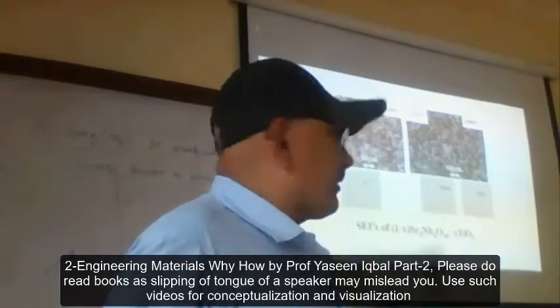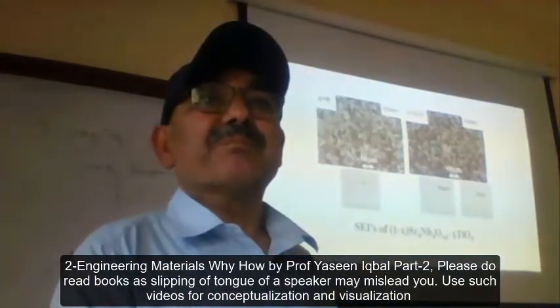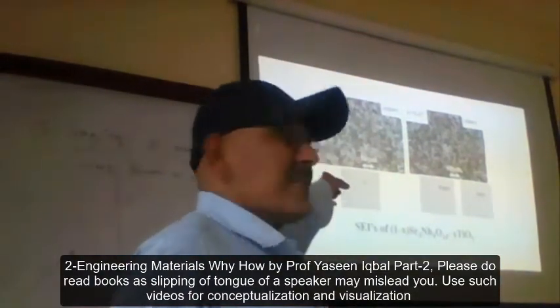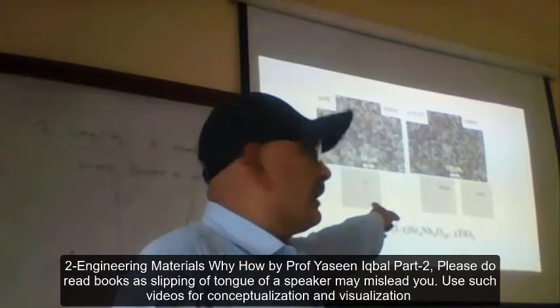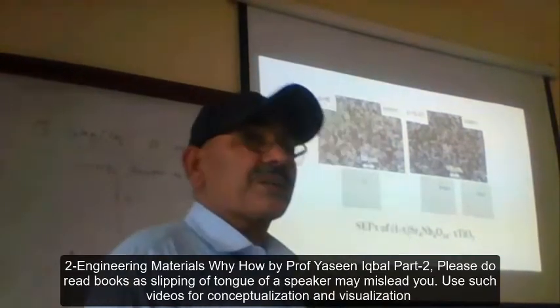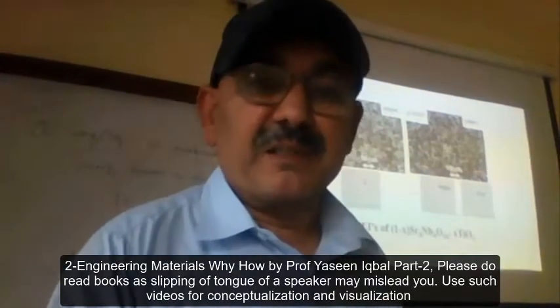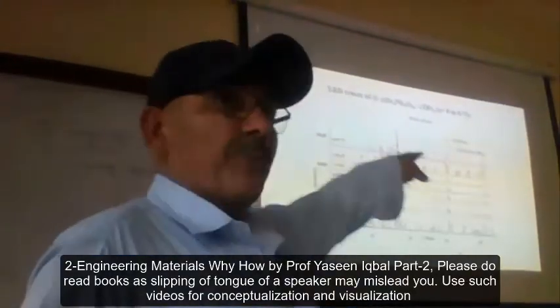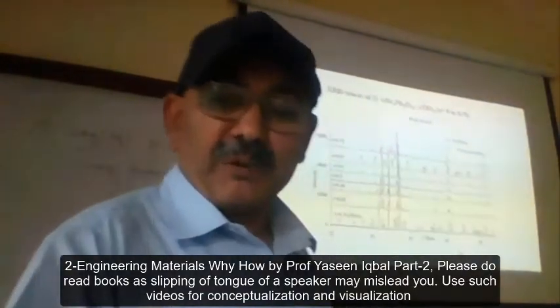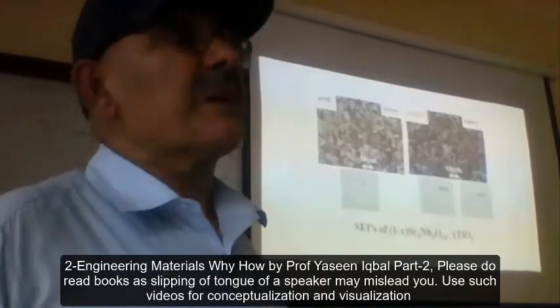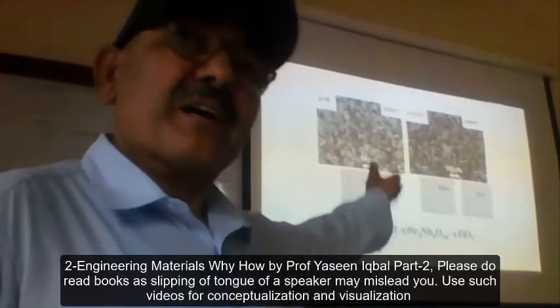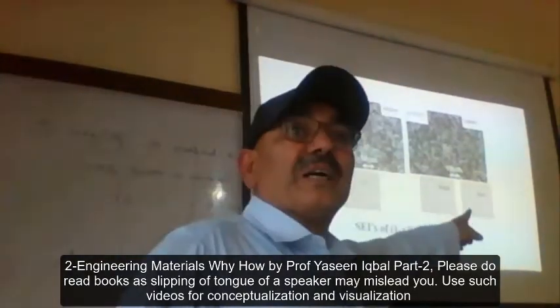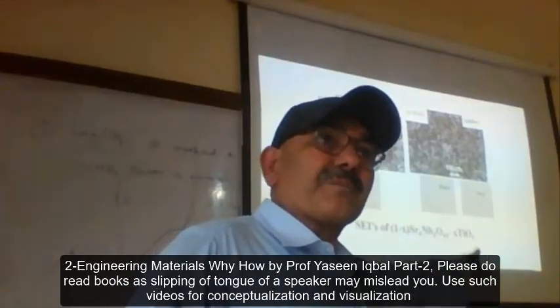But there, it is because of titanium. In these grains, you don't have titanium. And through that microstructure, you have one phase, strontium niobate, and the other one, strontium niobium titanate. Because of that, it is giving you different contrast.